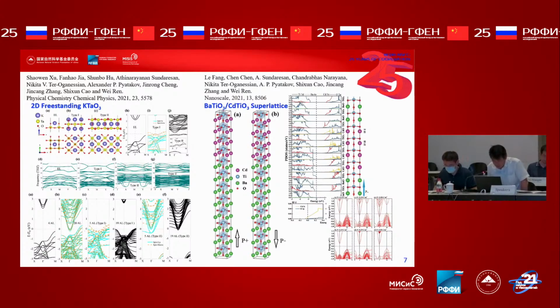This year, we predicted some fundamental properties of a polar perovskite KTO when approaching the 2D regime. If the atomic layer number is less than 14, the even layer systems are semiconductors, while odd layer systems are half metal, except for a unique KTO 5 as a semiconductor due to the Peierls distortion. The band gaps of even layer systems gradually decrease as the thickness increases. The odd layer systems are spin polarized metallic. Beyond 14 layers, even layer systems show ferromagnetic surface states, while ferromagnetism disappears in odd layer systems.